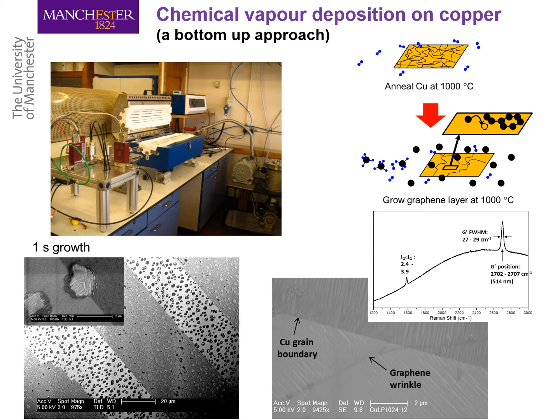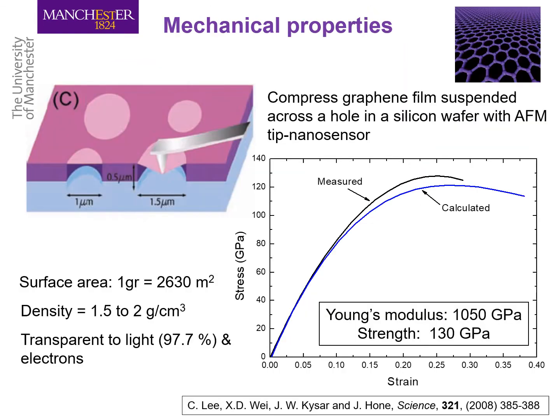In practice, though, no production method is perfect, and each has its difficulties, which lead to characteristic defects in the final material, and that can have an impact on mechanical performance. The mechanical properties of graphene: the Young's modulus is over 1 terapascal with a strength of 130 gigapascals, and a surface area where 1 gram covers 2,630 square meters. Graphene in its pure form is transparent to light and electrons.